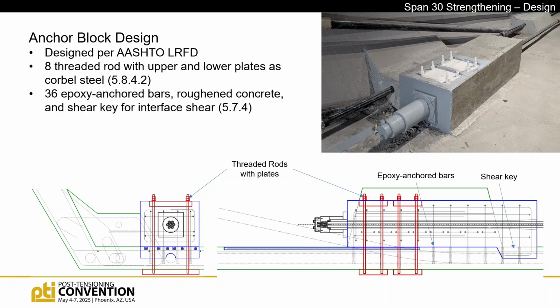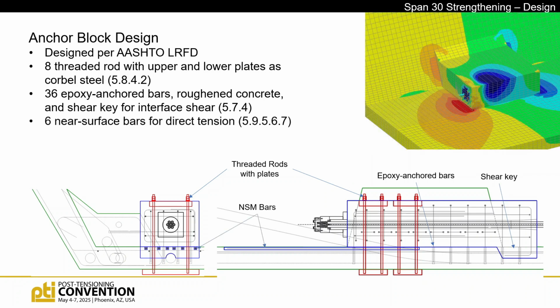We also used, for interface shear, 36 epoxy anchored rebars going into the bottom slab and into the temporary PT bar block, the erection PT bar block, roughened the concrete and added a shear key down at the end of it, at the toe end. We did use 6 near surface bars for the direct tension, and that's that bloom of red that you see in a finite element model that we were trying to resolve. It's a very lightly reinforced bottom slab, and those near surface bars are simply a groove that was dug into the concrete, filled with epoxy and a bar placed inside that.